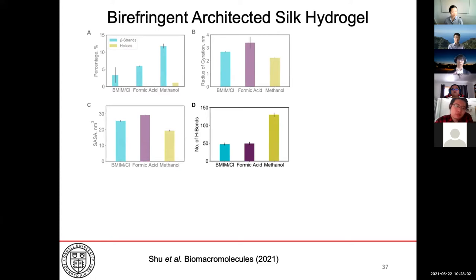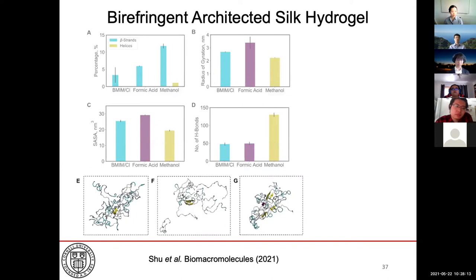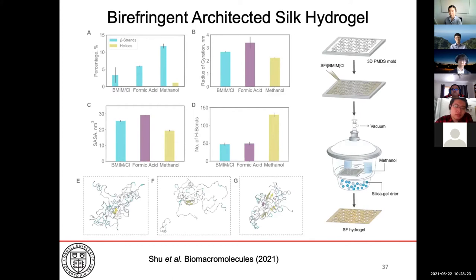And very clearly, methanol has a very, very strong effect on the structure of silk. And this is, again, very well known, but we actually managed to explore this using molecular dynamic simulations. And here is a visual of how using methanol processing, we can actually get a very dense and strong silk aggregation. And again, such a property was reproduced using experiments where they use a vacuum-based solvent exchange to exchange the solvents between the ionic liquid as well as methanol. And they cast this into a silk film.